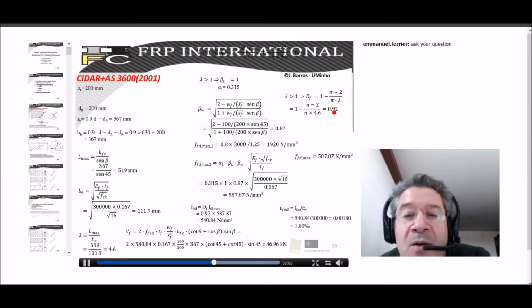Then we obtain a value of 0.92. For the DF, we obtain a value of 0.92. So this means that here we replace DF by 0.92. We evaluate the maximum value of the design effective stress. This is the minimum value between these two equations. So this is provided by the minimum value. So in this case, this is the FRP parameter. This is the tensile strength, and this is the safety factor.